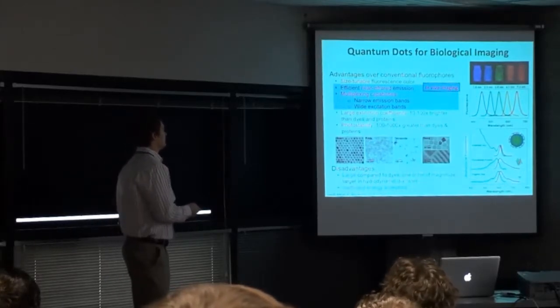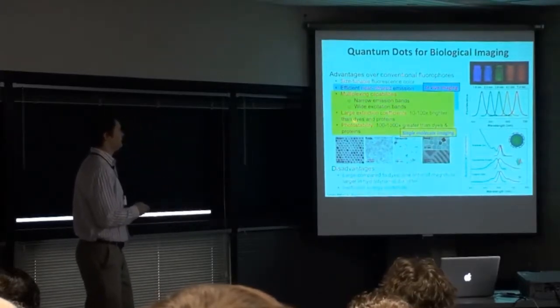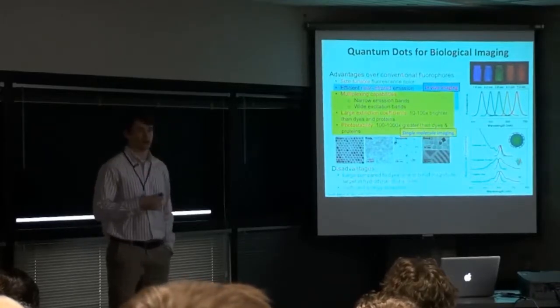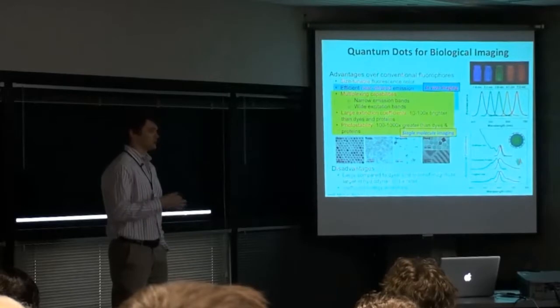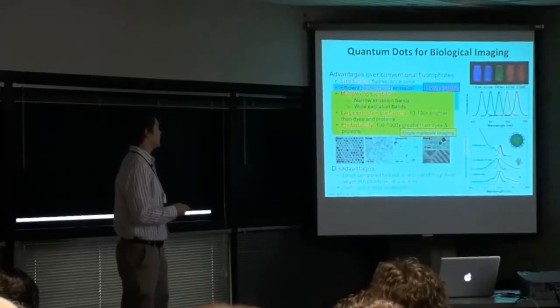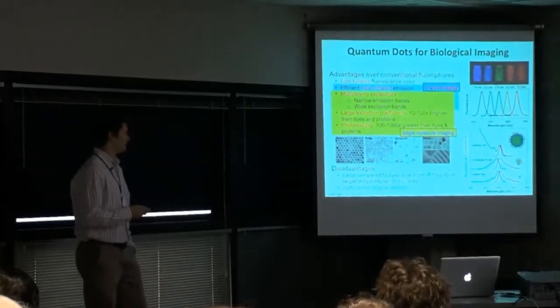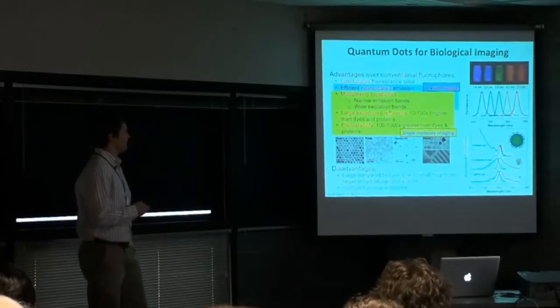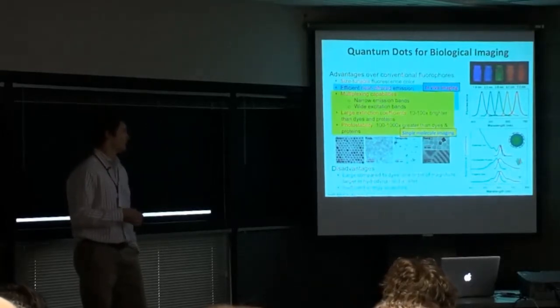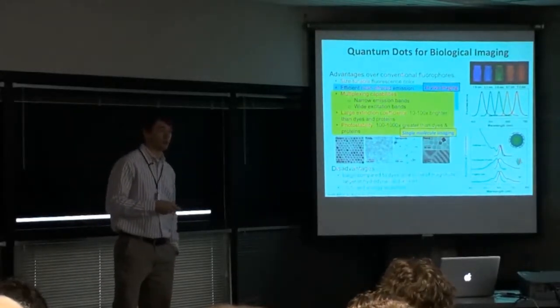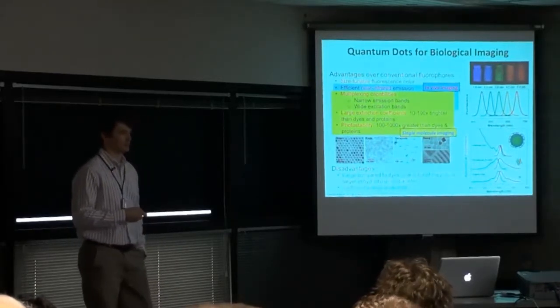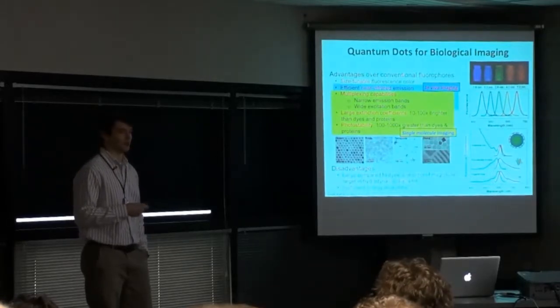For single molecule imaging applications, two other attributes come into play. They have very large extinction coefficients — typically 10 to 100 times larger than organic dyes and proteins — which translates to a roughly 10 to 100 times greater emission intensity assuming the same quantum yield. In addition, they are extremely photostable. You can image them for minutes to sometimes hours at the single molecule level without photobleaching, as opposed to organic dyes and proteins which usually have just a few seconds of observation before they oxidize and decay.